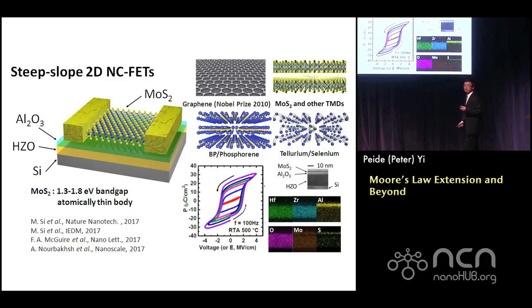Now what we realize is, for the ferroelectric material, we still use ALD. We grow a particular material called hafnium zirconium oxide. This material is a ferroelectric material, as I measured here. Ferroelectric means it can switch up, switch down, as shown here. So we have the ferroelectric material here. Now for the channel, we use a semiconductor channel, but we use so-called 2D materials. This is a very popular research topic worldwide.